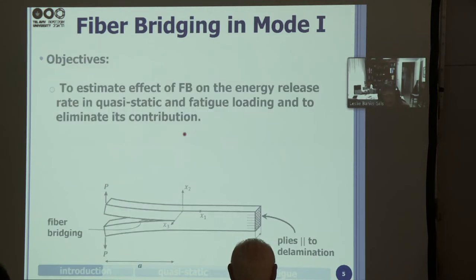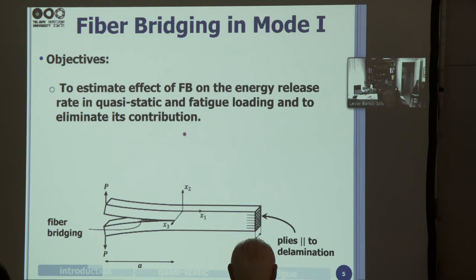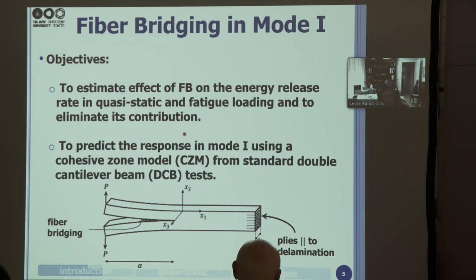using the same material. So what we want to do is estimate the effect of fiber bridging on the energy release rate in both quasi-static and fatigue loading, and to eliminate its contributions to get the net fracture toughness and the net fatigue delamination propagation properties. So to predict the response in mode one, we're going to use a cohesive zone model from a standard double cantilever beam.